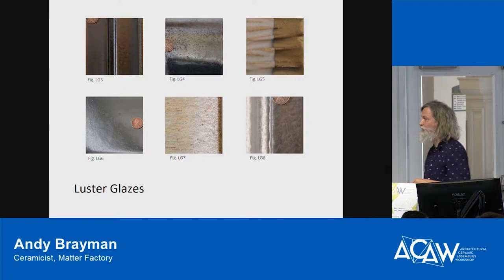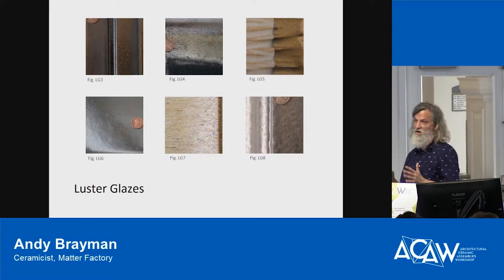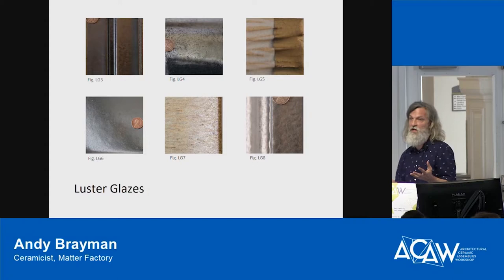And then I know in recent years the team here at UB had done research on iridescence and looking at glazes that fall into that category, and had some real successes narrowing in on glazes that have that effect. And this is where we get back to the question of control, right? You can find glazes that will do things, and then they may be very difficult to replicate. It wouldn't be because Boston Valley doesn't know what they're doing. It's because the variables are so sensitive, the application thickness of glaze being one of the prime culprits of variation in the process.